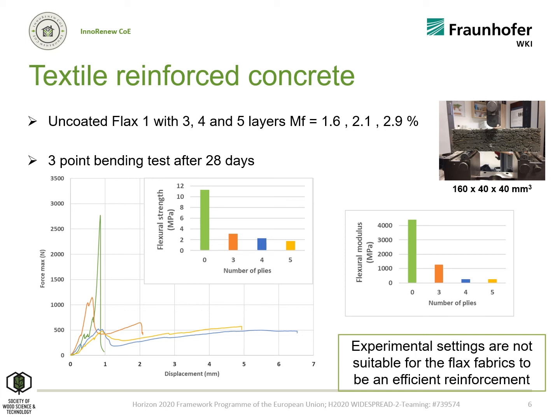The second issue is the grain of the concrete that is quite coarse, and the opening of the flax 1 fabric is too small for the cement particles to penetrate the spaces and to create a good anchorage between the fabrics and the concrete, so the load transfer is here limited.